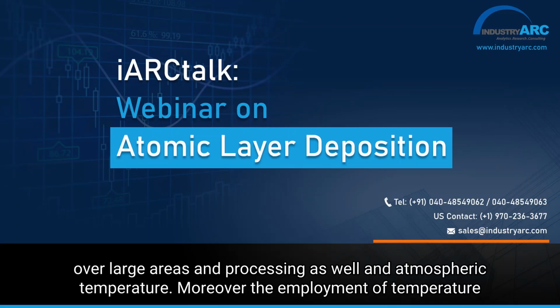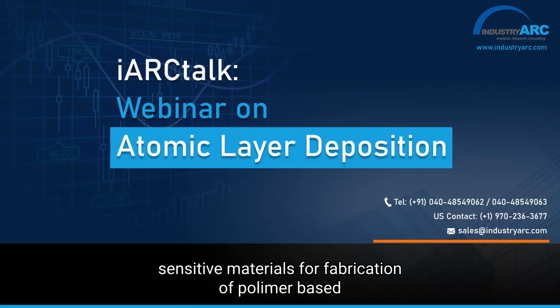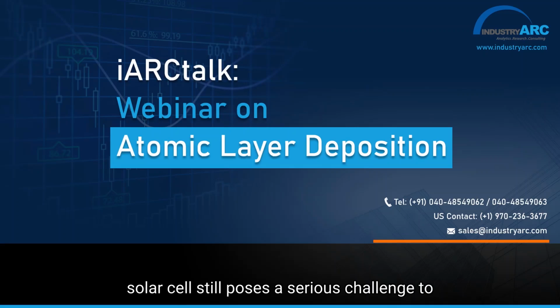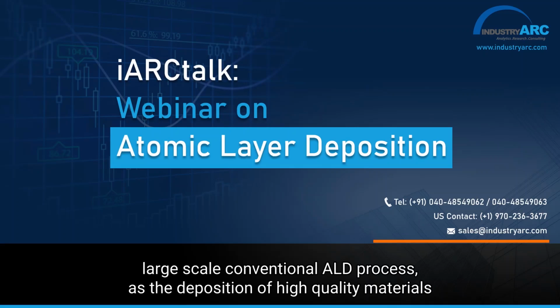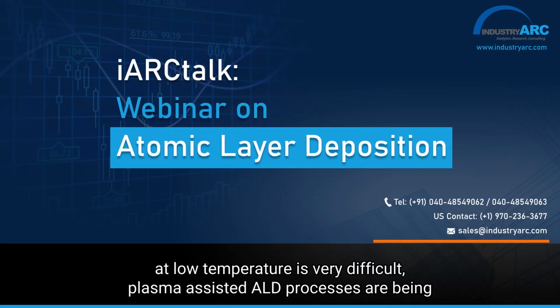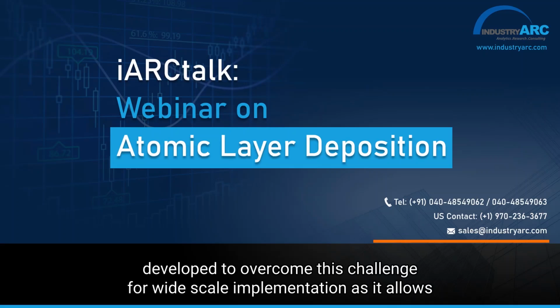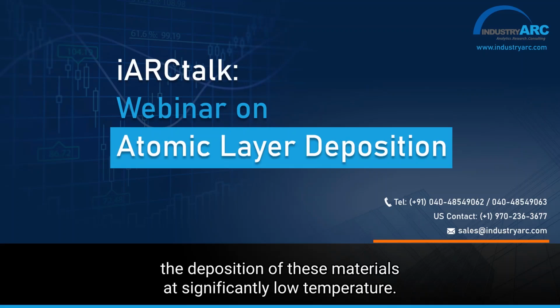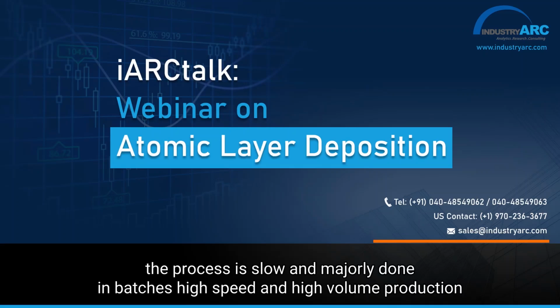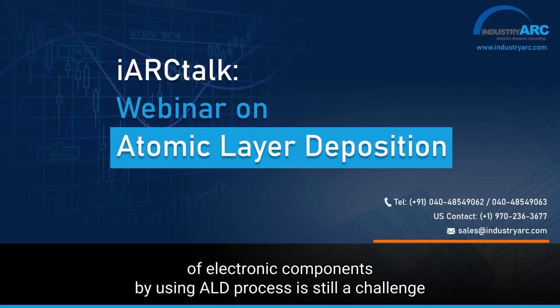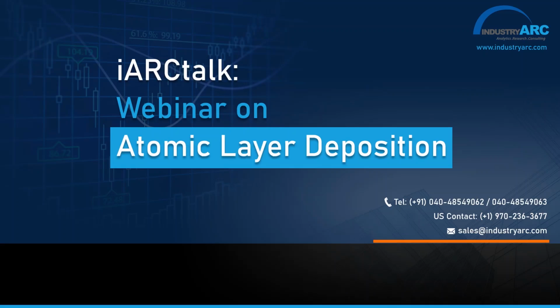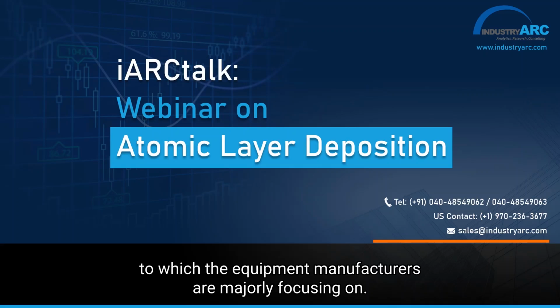Moreover, the employment of temperature-sensitive materials for fabrication of polymer-based solar cells still poses a serious challenge to the large-scale conventional ALD process, as the deposition of high-quality materials at low temperature is very difficult. Plasma-assisted ALD processes are being developed to overcome this challenge for wide-scale implementation, as it allows the deposition of these materials at significantly low temperature. Apart from this, the process is slow and majorly done in batches. High speed and high volume production of electronic components by using the ALD process is still a challenge, on which the equipment manufacturers are majorly focusing.